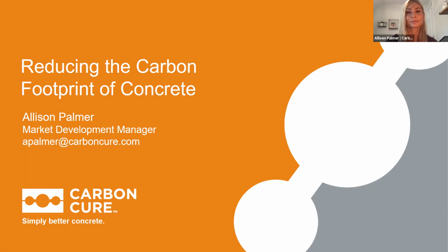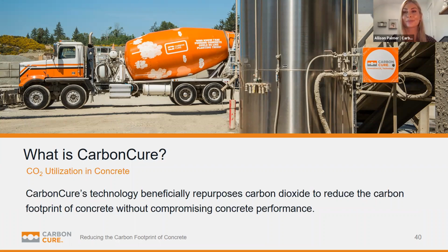So with that, what is CarbonCure? We've developed a technology that introduces CO2 that is captured from large industrial emitters like fertilizer or ethanol plants, and injects it into the concrete mix during mixing, just like any admixture. Once introduced into the mix, the CO2 chemically converts into a mineral and is permanently trapped in the concrete, even if the building is destroyed later on. Ultimately, this process improves the strength of the concrete, which allows us to optimize our mix designs and reduce the cement content of our mix by about 5 to 6%, the material with the highest carbon impact, without impacting any fresh or hardened properties. I'm going to go into this process in a little bit more detail, but ultimately the message that I want to come across is it's the same concrete being delivered to your job site, but with a reduced carbon footprint.